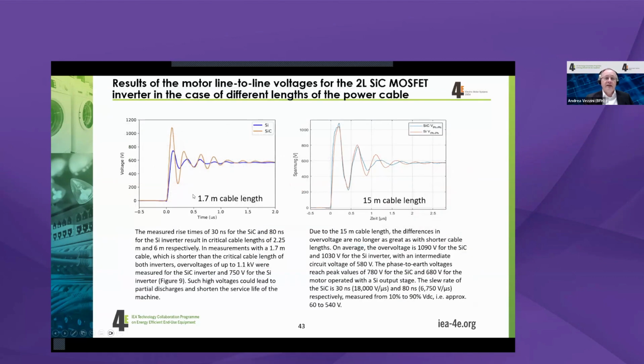From our testing here, with a very short cable length, silicon versus silicon carbide, with switching speeds of about 5 or 6.7 kilovolts per microsecond for the silicon and about 18 kilovolts per microsecond for the silicon carbide, you see that for a short cable length, the over voltage for the silicon carbide can be much higher than the one for the silicon based. But what is important is that as soon as you go for a cable length which is over the critical cable length, you will see over voltage in both cases, and they reach the critical value, which is about 2 times the DC link voltage.